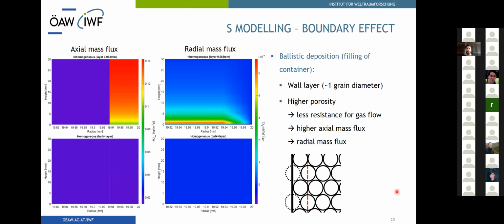The simulations were not only used to verify the measurements, but also to analyze certain boundary effects that arise due to finite sample dimensions. An example for such an effect is that when a material is filled into a container, the grains which are directly at the wall cannot pack as tightly as in the center. The result is a slightly higher porosity in a thin layer at the sample wall interface, through which the gas can flow more easily. These images show the simulation of this effect for a sample with similar properties as the glass bead samples with the smallest beads. The bottom images show the quantities in the case of a homogeneous sample.